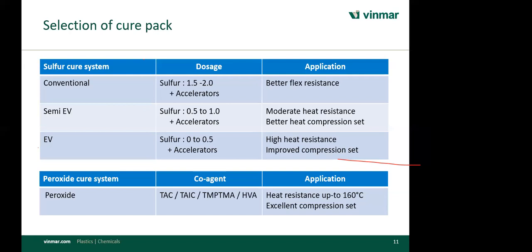For high temperature resistance of the product, which is continuous use at more than 150 degrees centigrade or more, we recommend the peroxide cure. And peroxide also needs some co-agent, either TAC or TAIC or TMPTMA or HVA, depending on your system.